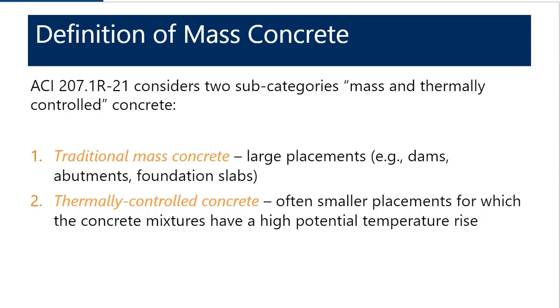And these are typically smaller placements. And in these cases, the temperatures are more governed by the specific concrete mixtures, which have a high potential for temperature rise. And this may be because they contain a lot of cement or cementitious material, or it may be because they're designed to achieve very rapid early strength gains. The more rapid your strength gain, the higher potential you have for early age temperature rise in your mass concrete.